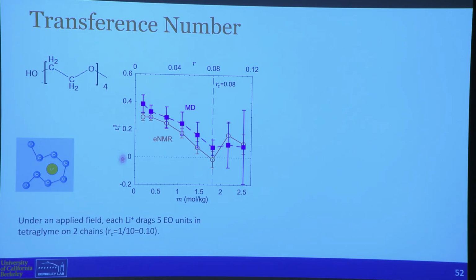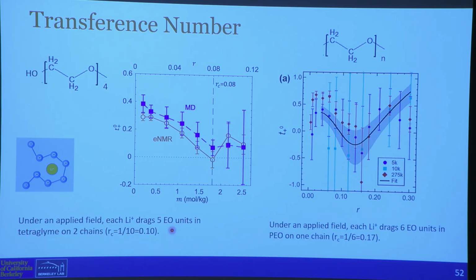When you have a lithium ion, it needs 5 oxygens around it, so it drags 2 chains with it. And when you ask the question, when is this construct pervading the entire cell, you'll get r equals 0.1. So using this simple idea that the solvent is being dragged by the solvation shell, you would get a transference number of 0 at 0.1, and we measure it at 0.08. Of course, that's because of complexities.